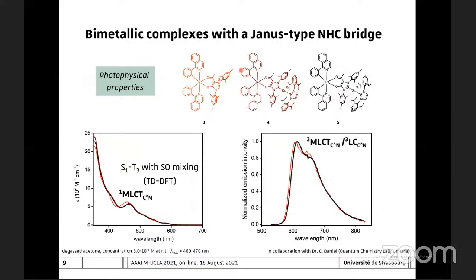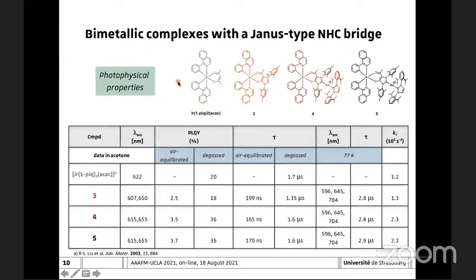On the other hand, in the emission spectrum, we also observe very similar emission profiles attributed to the triplet metal to ligand charge transfer state, with a very small hypsochromic shift, again for the monometallic complex.